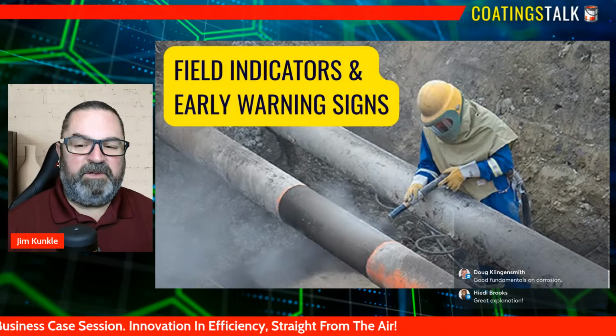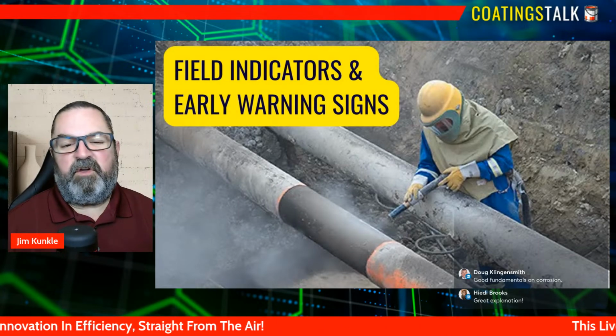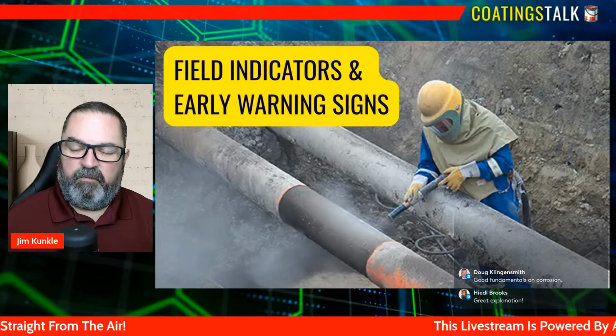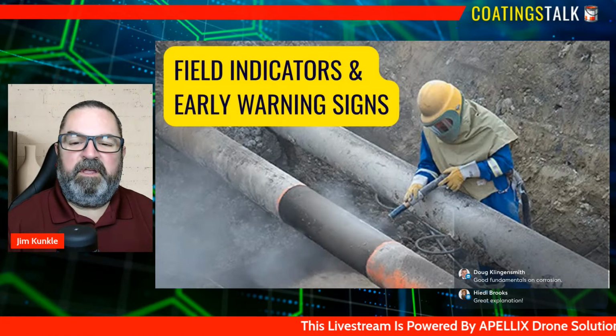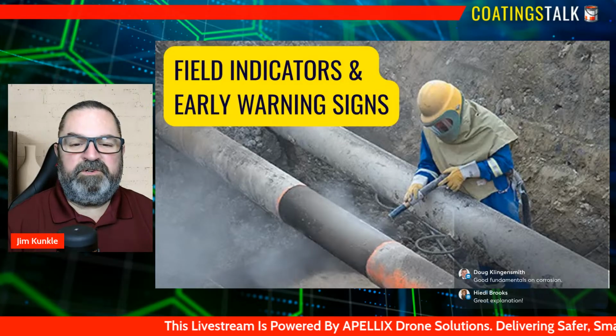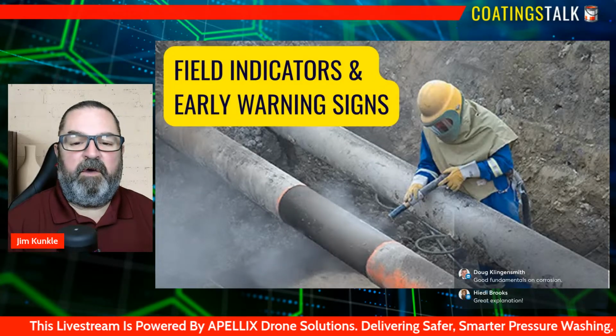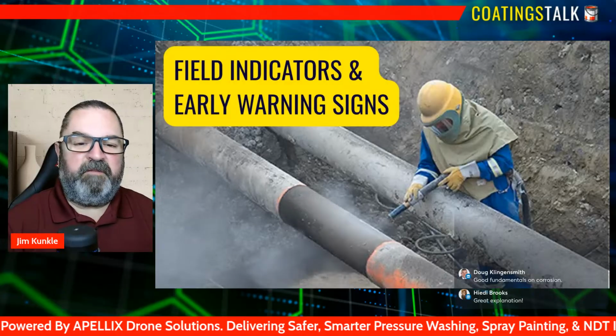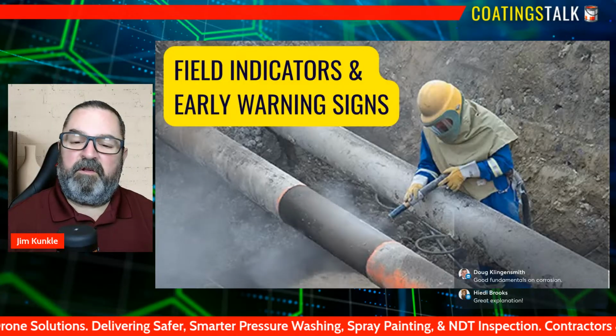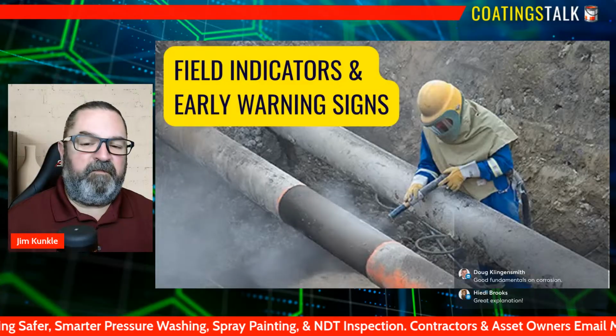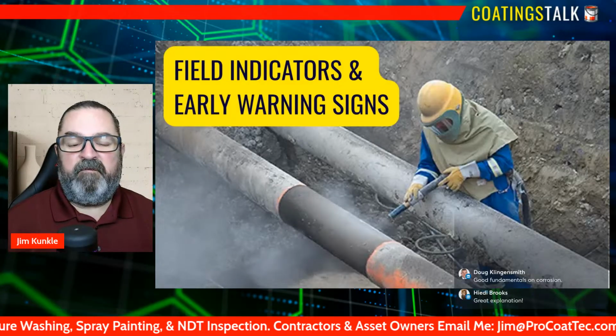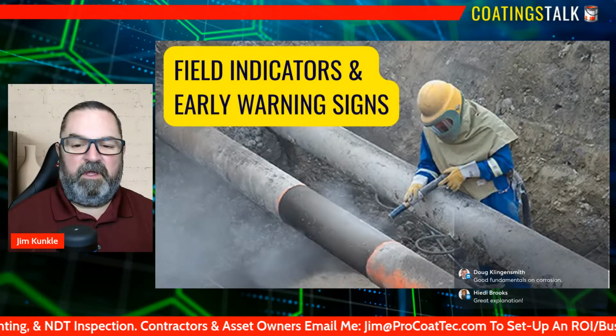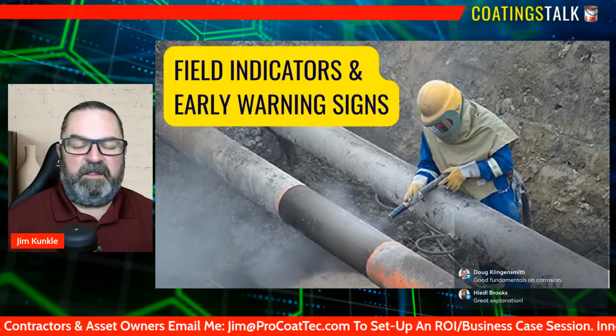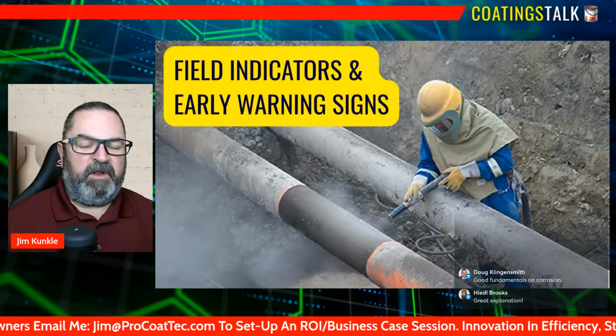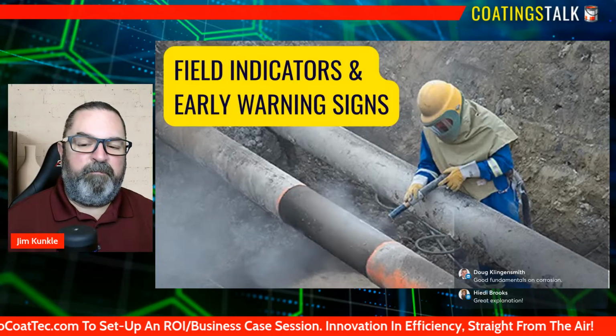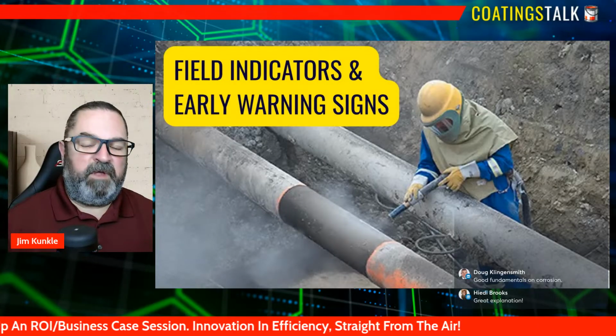across the entire operation. Surface changes, coating failures, discoloration, and moisture water traps, as I mentioned, these are always clues that corrosion can and is beginning to take hold. So they are very easy to miss if you're not intentionally looking for them. A surface that once appeared smooth and uniform may start to feel slightly rough, gritty, or uneven, and you might notice the dulling of the coating, small areas where the gloss has faded, the subtle texture differences that don't match the surrounding metal. These early shifts are important because they might signal that the protective barrier is being compromised.